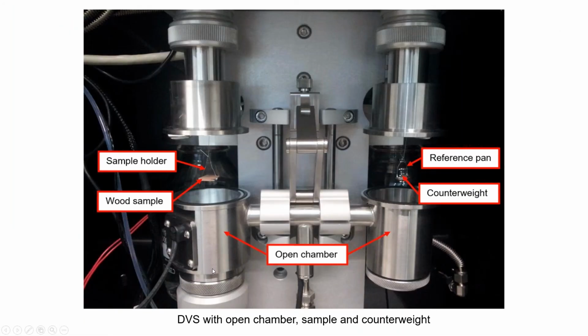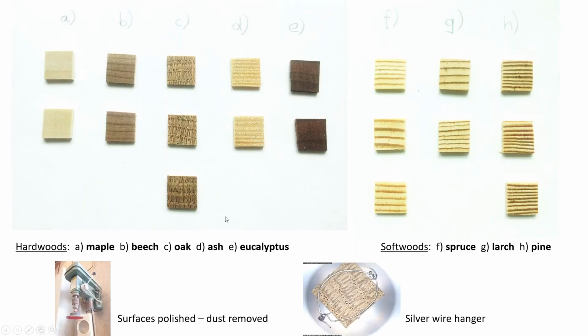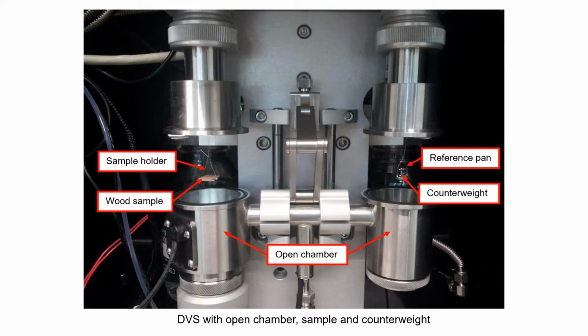You know, the camera looks on the left side from below. So the lower side of the sample needs to be quite visible. With the quartz hangers, we always had reflections and problems. Here, you see directly the surface. So that was quite handy and easy to get good pictures.